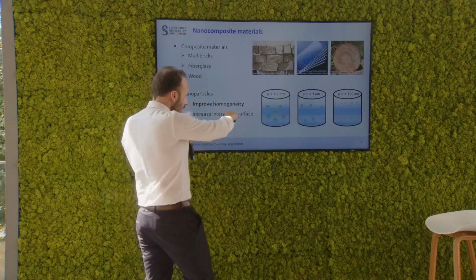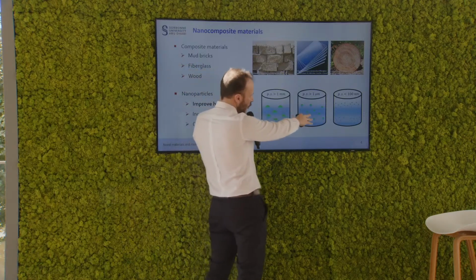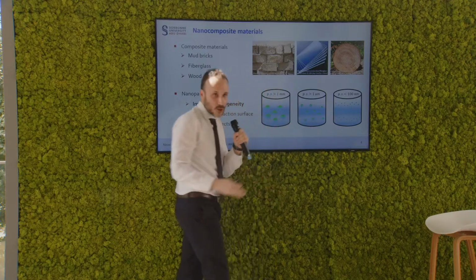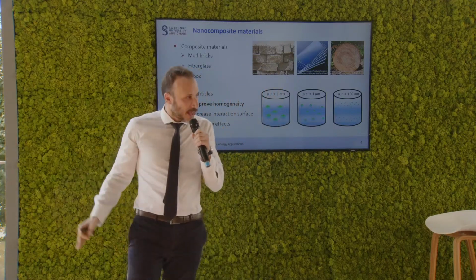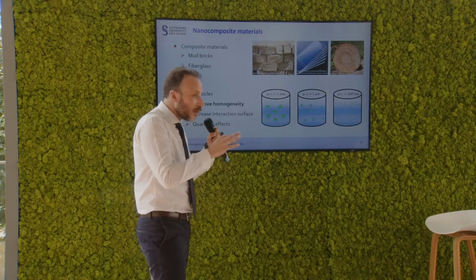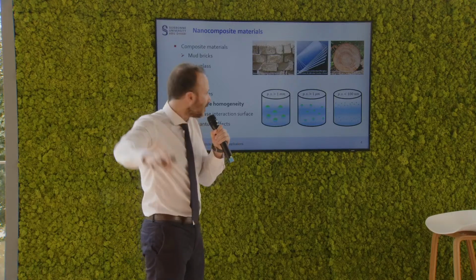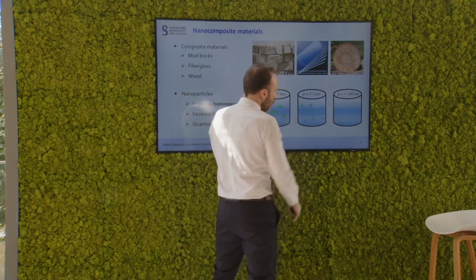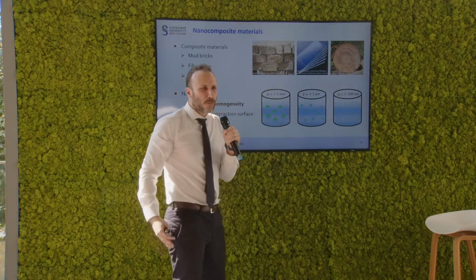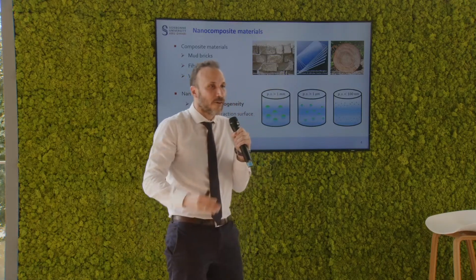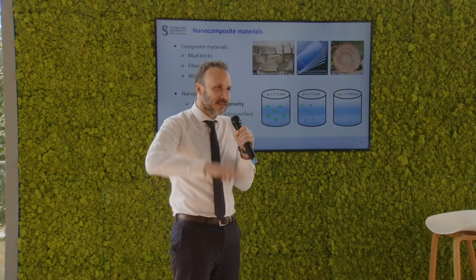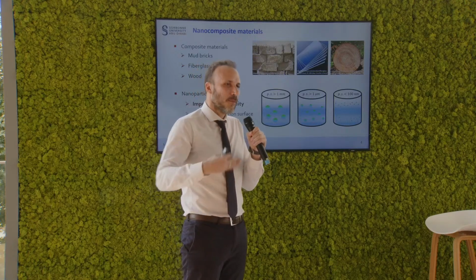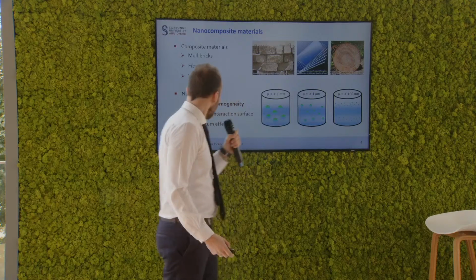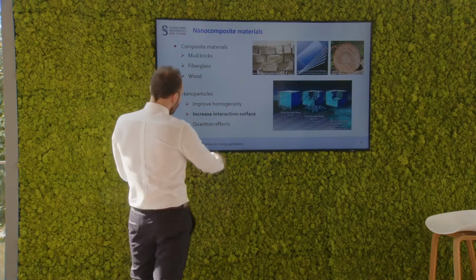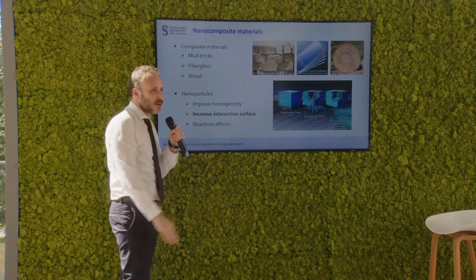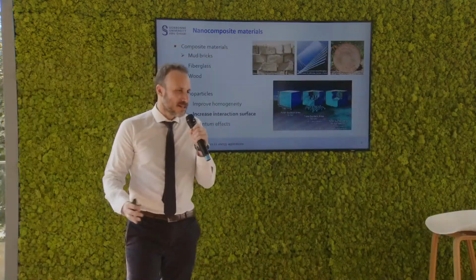As we reduce significantly the size of particles that are dissolved inside the solution, and we go to the nanoscale, then if we let them float and disperse nicely throughout the entire solution, all the areas look pretty much similar. That means they will carry the same type of properties in the entire body of the solution, making the solution homogeneous. The second reason is that nanoparticles increase the interaction surface at a very large scale.